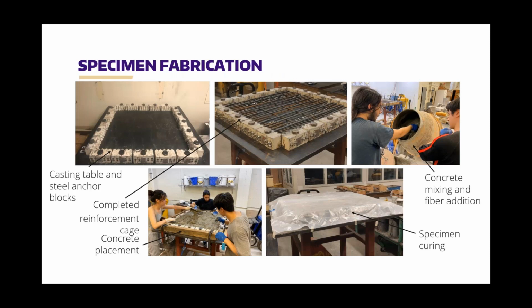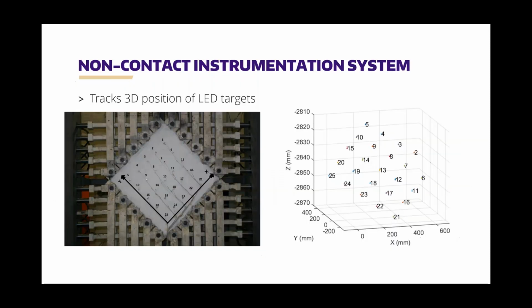This is what specimen fabrication looks like in our lab. You can see the casting table there, the steel anchor blocks. Those are what allow us to attach the reinforced concrete panel to the test frame. You can see the fiber addition and the curing there. So once you get this panel cured for at least 28 days, then it comes into the panel element tester. You can see some of the weight.